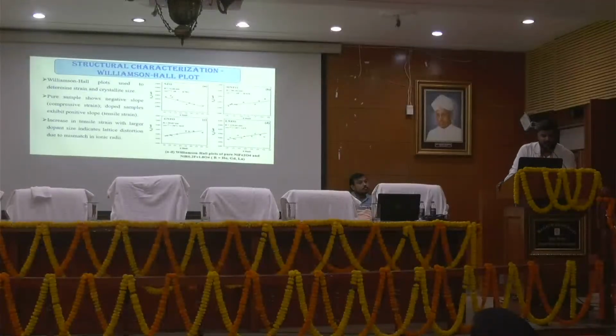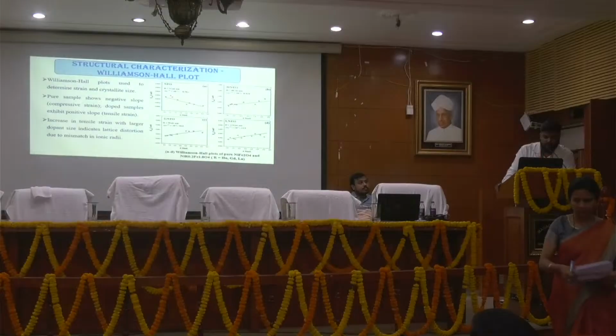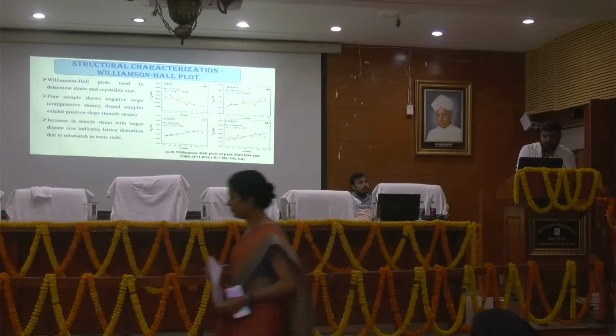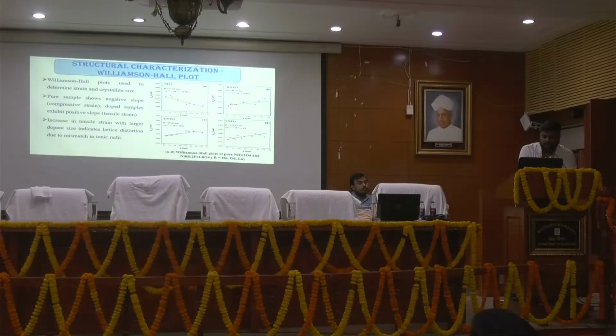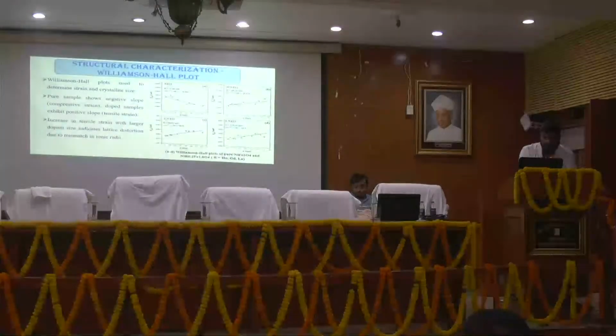And this is the Williamson-Hall plot through which we have calculated the strain and particle size of the sample. In the pure sample, in the first figure, you can see that there is a negative slope in the pure NFO, because there is no strain in the pure sample.